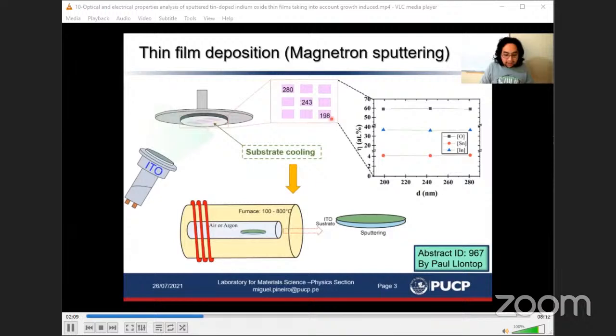Using EDS spectroscopy, we obtain the elemental composition, and we can see in this figure the elemental composition doesn't change with increasing thickness. Then thermal annealing is done at different atmospheres such as air or argon in order to modify the optoelectronic properties.